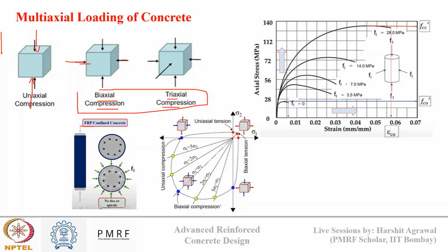If you see in this curve also, under uniaxial loading the strength was this, but with any amount of biaxial loading, the strength increases. If I have compressive stresses acting from the sides, it will increase the strength of concrete under axial loading also. The same is seen here with the confining stresses: as the confining stresses increase, the axial stress of the concrete also increases because of the confining effect those forces create. However, if this force is tensile in nature, it will weaken the concrete rather than strengthen it, because tensile stresses are already generated due to the loading, and now these stresses are also there. So the direction in which the confinement is applied also becomes important.